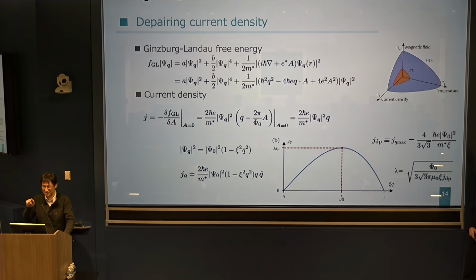In reality, if we introduce current, then we have a magnetic field that makes vortices. If there is no defect or grain boundary, and then if there is no pinning of vortices, then vortices flow in a sample. That makes a resistivity. And so to have a large enough current, those vortices must be pinned or fixed. In this depairing current, we assume that the vortex doesn't move. So for the precise estimation of this Jc, we have to study the pinning of vortices. And that is also a very important future problem, ab initio calculation of vortex pinning.